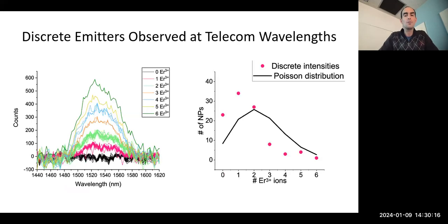And with that, we were able to observe even at 1550 nanometers, which is quite challenging in our current setup, these discrete levels in the emission corresponding to having just one emitter, two emitters, or three, at the single photon wavelength we want to use for quantum information approaches. So that's a good sign.